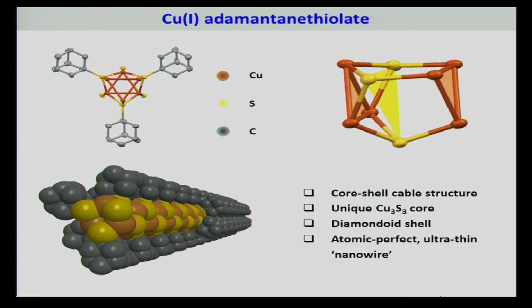And then on the outer rim, you have the diamondoid surrounding this core, really forming a core shell cable kind of structure. And to remind you, this is really atomic perfect, and this is an ultra thin nanowire. This is only 3 atoms thick in the core, and I don't think anybody else was able to make a nanowire this thin.